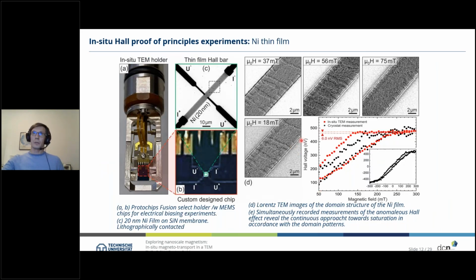And if we do so, we will simultaneously, for every magnetic field value, acquire a Lorentz TEM image and measure the Hall voltage. And this is shown here on the right-hand side. So let me first guide you through the images. You see in the Lorentz TEM images different domain patterns popping up. You can differentiate between the domains by these bright and dark lines, the domain walls. And what you can see is that when we increase the magnetic field from 18, 37, 56 up to 75 millitesla, these domain patterns are vanishing.